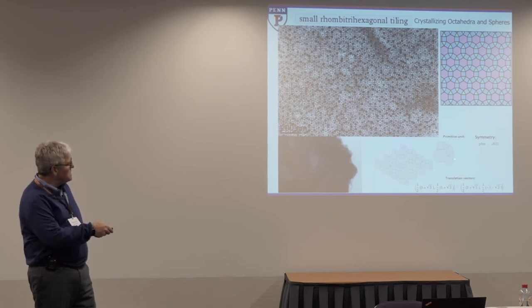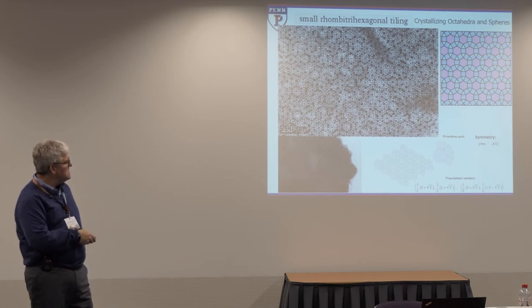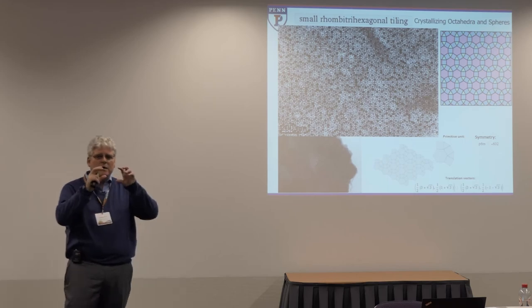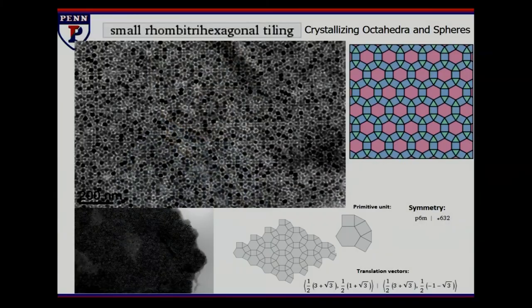So pretty complicated symmetry. And yet this is forming naturally from the self-organization of the materials just by taking two particles and making one of them not quite a sphere. It's got truncated corners, so it's got octahedral symmetry. And so with those two pieces, they can't quite fit together, or don't choose to fit together, to make a simple FCC or HCP structure. The best way that they can minimize the overall energy is to start looking for higher order symmetry. So it's a pretty complicated crystal structure, but it comes from very simple building blocks in terms of that design. But it's still crystalline. It does have a repeat structure and well-defined translational vectors.